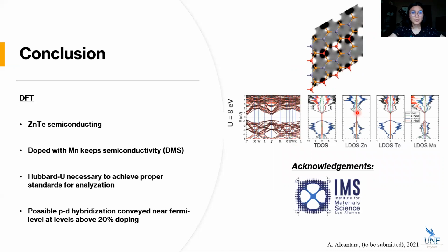And so just to wrap all that up, density functional theory was used. We use zinc telluride. We show that it's semiconducting. Doping it with manganese keeps it semiconducting. Hubbard U was necessary for the proper analysis. And most importantly, we show a possible p-d hybridization near the Fermi levels, which is consistent with the experimental data.